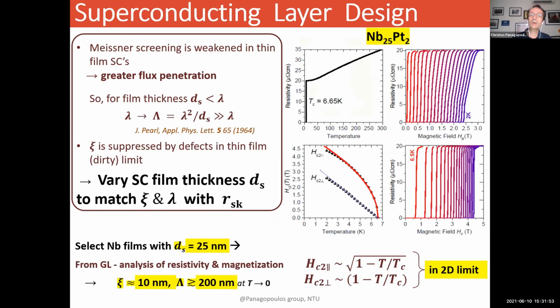And from Ginzburg-Landau analysis, both of resistivity and magnetization, we estimated the superconducting coherence length to be roughly 10 nanometers, and the Pearl length to be approximately 200 nanometers as we approach 0 Kelvin. On the right-hand side, you see magnetotransport data from our niobium films. Note that these niobium films, because they are so thin, are capped with a very thin platinum, which I will touch upon soon. And by looking at the data here, the upper critical field indicates that indeed we are in the two-dimensional limit.